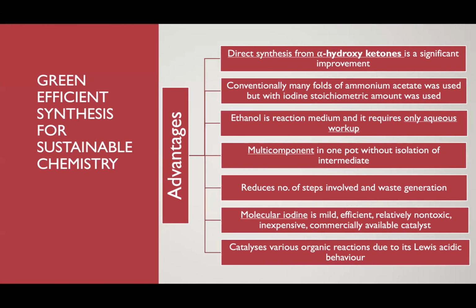When we look at the reported literature methods, they were using ammonium acetate in many folds, a very high amount of ammonium acetate was used. But in our synthesis, we reduced it to almost stoichiometric amount. We used ethanol in comparison to other hazardous solvents, which had easy workup. You simply had to put water and the product will come and we will filter it. It is a multi-component synthesis where you can reduce the number of intermediates, thereby reducing the waste material and the number of steps. And molecular iodine, as you all know, is a mild reagent, easily available. It has several advantages.